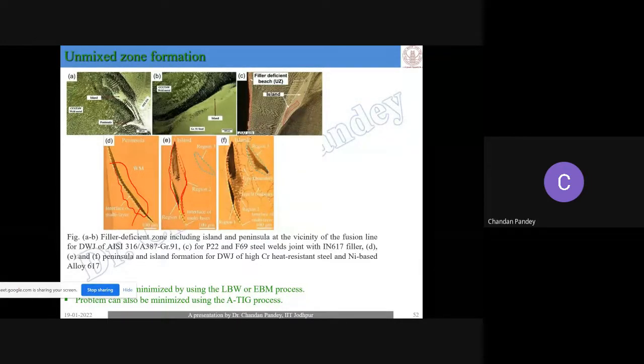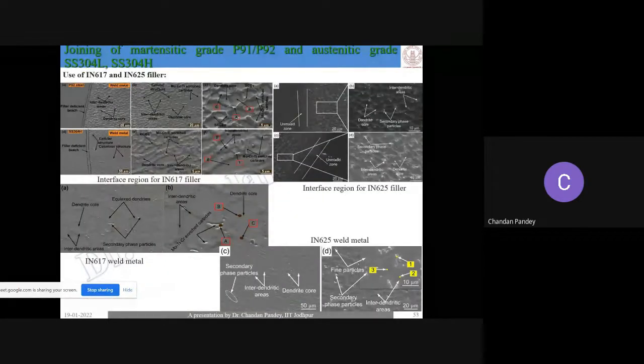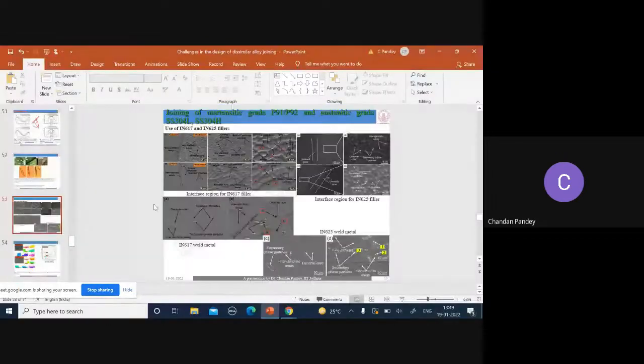So again, the major problem associated with that is the formation of the unmixed zone. So how can we remove that unmixed zone formation in dissimilar joints? That we can minimize by using the autogenous welding process, because in case of the autogenous welding process, we are not going to use any filler metal. So in that case, we can avoid the problem related to unmixed zone formation. So I'm going to stop here. There are so many things, but I think up to here it is sufficient.